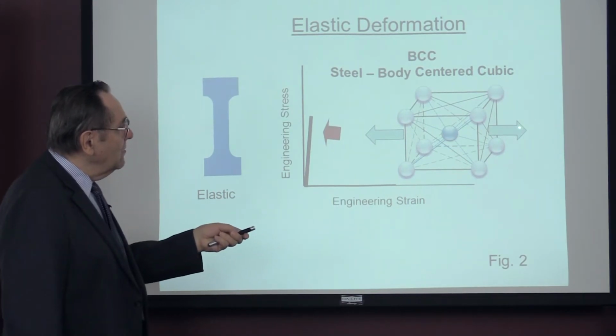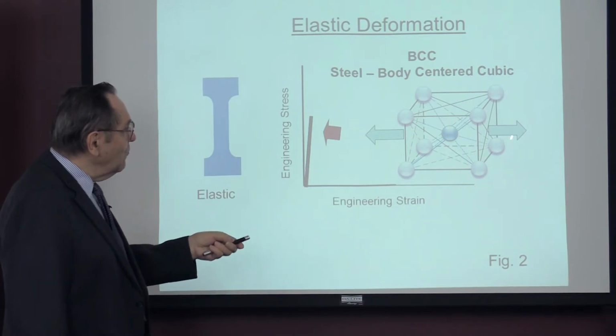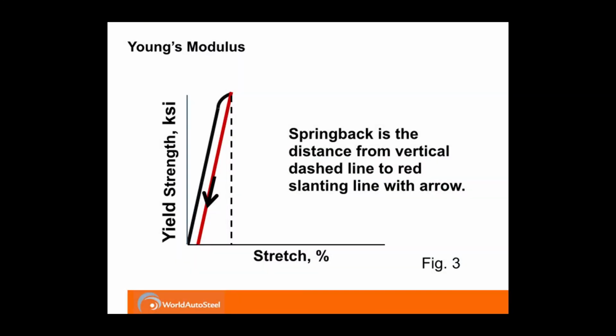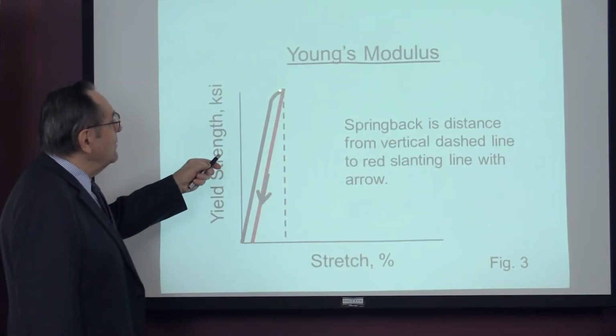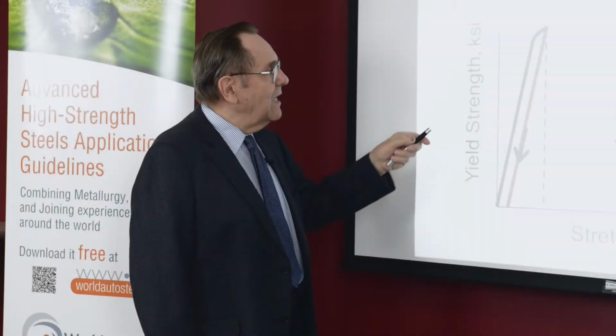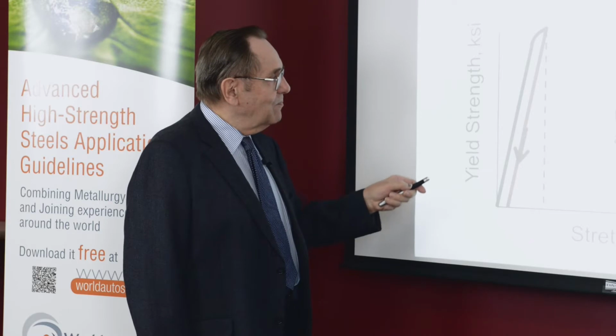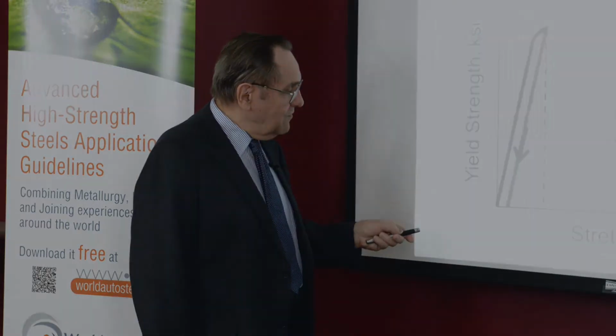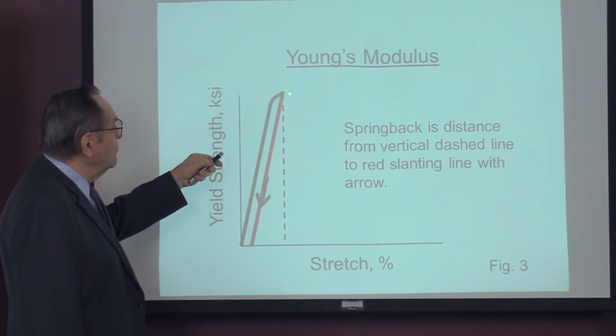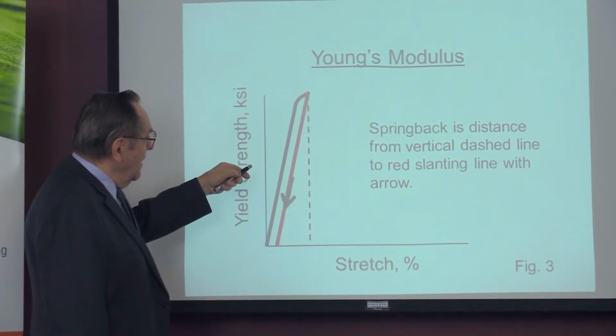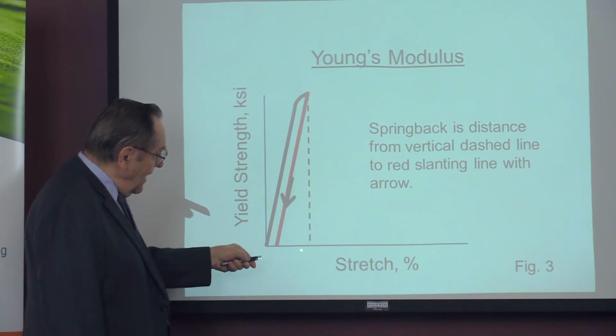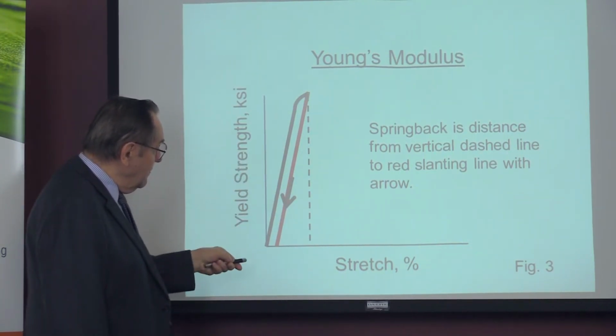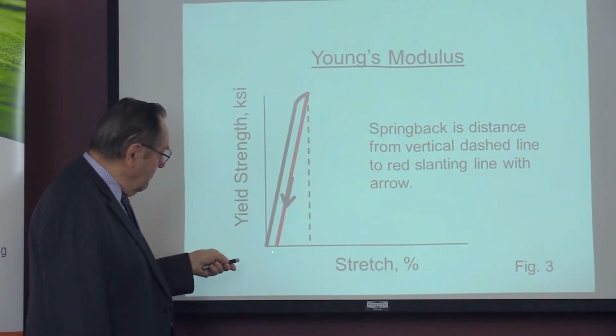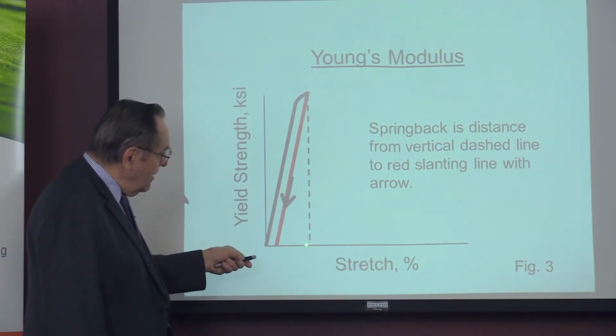Well, as you pull the metal here, you climb up. When you release the forces, it snaps back down. At one point, however, you reach a distance where you have both elastic and now you start with permanent plastic deformation. And this is often dictated by a line which goes parallel to the elastic modulus, offset by 0.2%. You come up here and you mark that, and that is the yield strength. And if you take this down straight, this is the elastic portion of what you have in the metal up here, and this is your plastic deformation. So you can see that you have a major portion of deformation all tied up there.